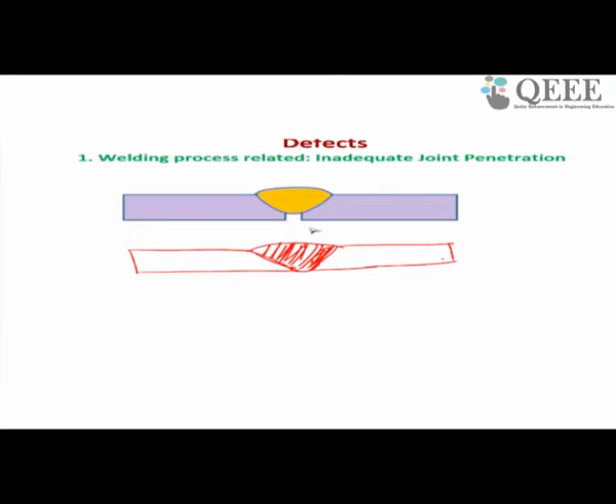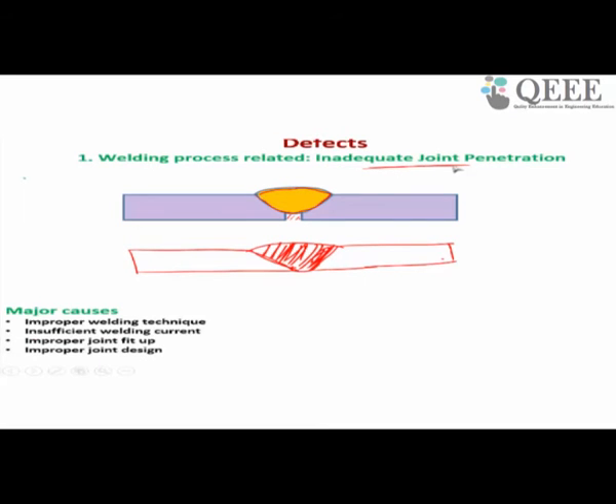But because of improper heat input, it will not melt and join, and it will have something like this, and it will have this gap. This is called inadequate joint penetration. It happens because of improper welding technique, insufficient welding current, improper joint design and so on. So you have to do it properly. You have to calculate and do proper joint design before welding.